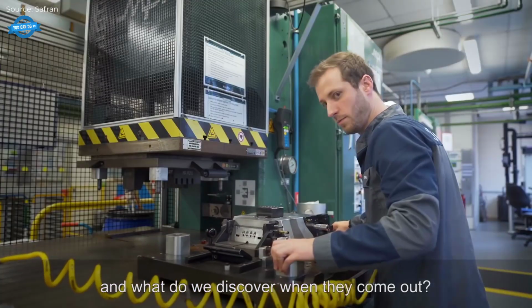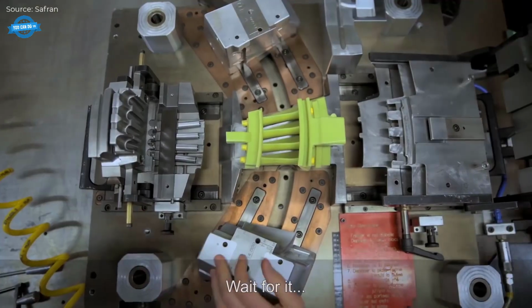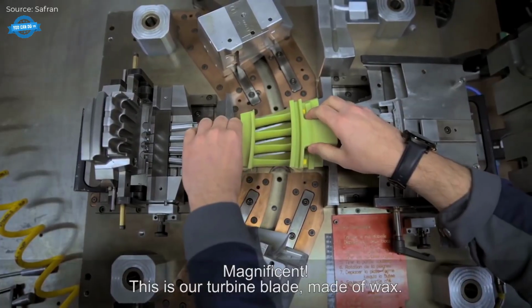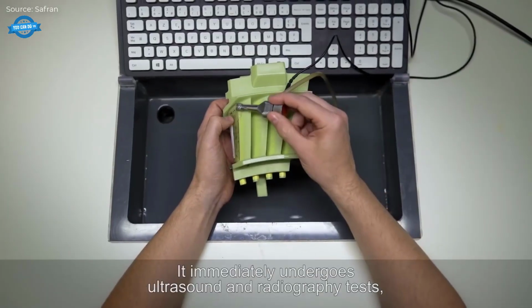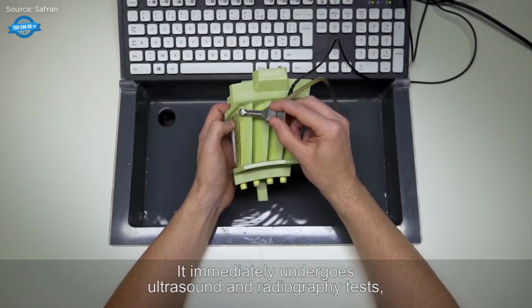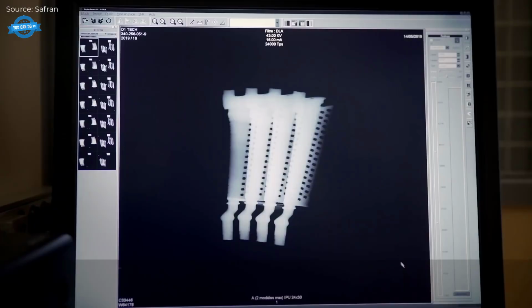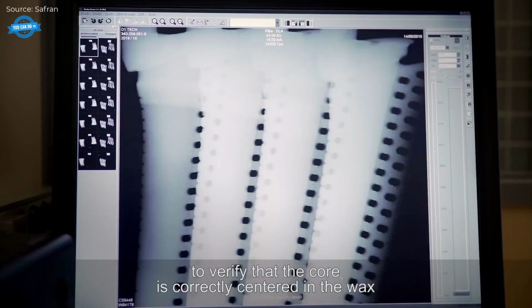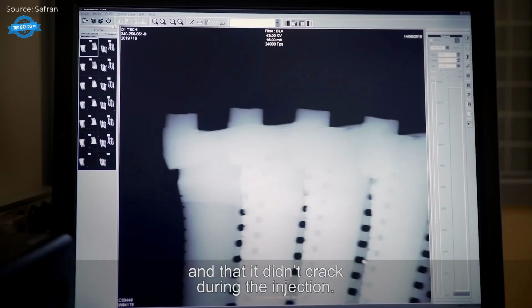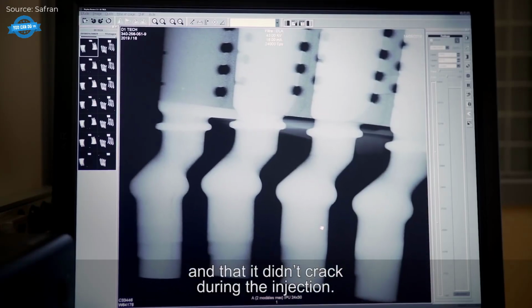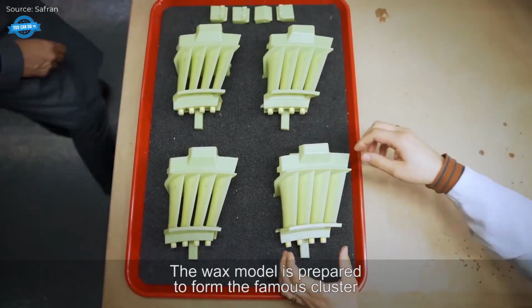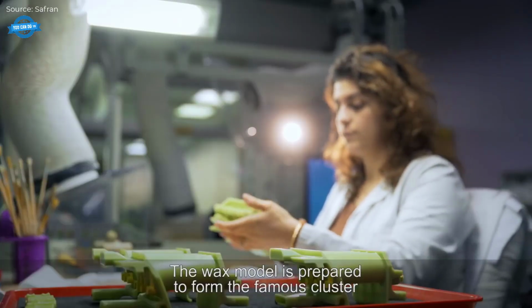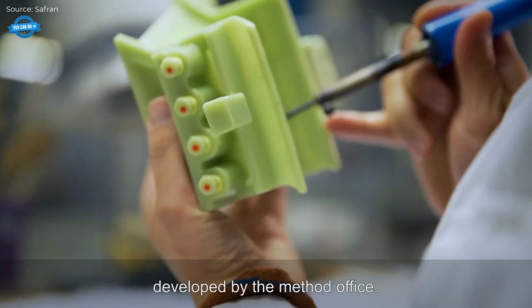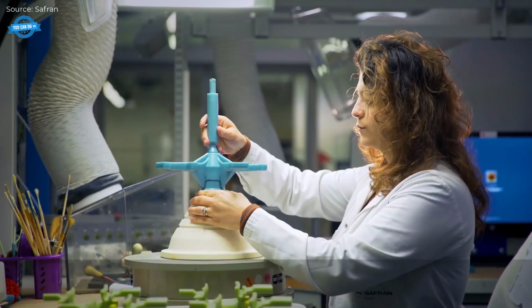Each core is meticulously checked for defects and deburred before it is placed inside an injection mold. 4 cores in the case of this LEAP engine turbine blade are positioned in the mold to form the blade's complex cavities. Once aligned, molten wax is injected to form a replica of the turbine blade around these cores. This wax model undergoes ultrasound and radiographic testing to ensure the core is accurately centered and has not developed cracks during injection.